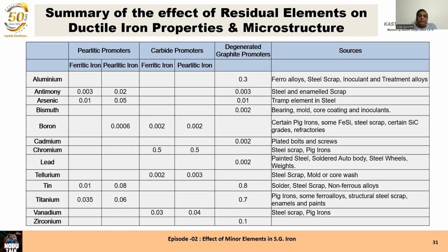This is a summary. I think it will be useful for you to tell your scrap supplier to make sure where the sources of these bad elements are coming from. Aluminum, antimony, arsenic, bismuth, boron, cadmium, chromium, lead, tellurium, tin, titanium, vanadium, zirconium: their levels required as pearlite promoters in ferritic irons, as carbide promoters in pearlitic iron, and as degenerate graphite promoters are given, and the sources are given over here. Please make sure that your steel supplier has this information so that he doesn't bring the wrong elements into your charge materials.